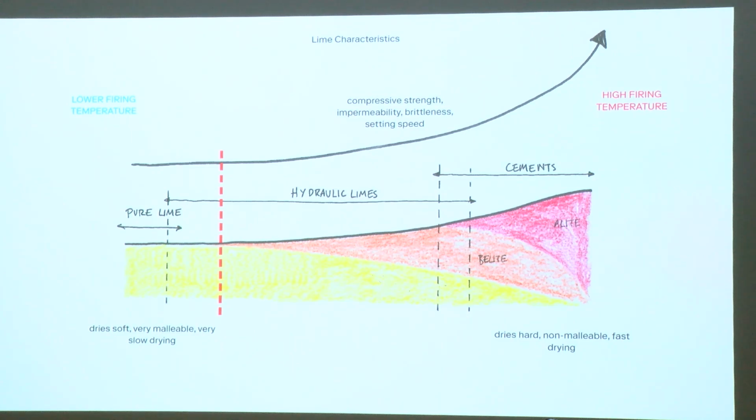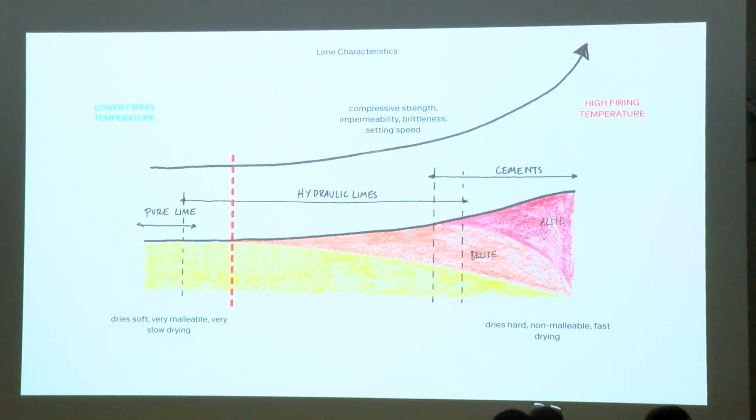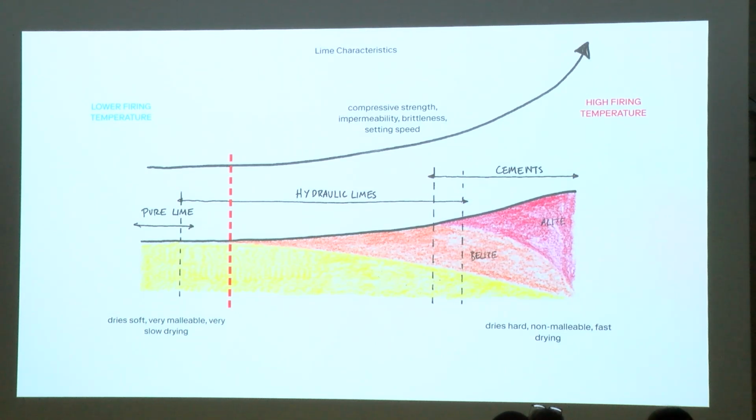So you could effectively take the brick, burn it again, and repeat that process. That's where lime becomes quite an interesting material, because you can just keep going around the cycle. And the sequestration of carbon when it carbonates is theoretically carbon negative relative to the carbon produced in the firing process. We're not using a lime at that end of the spectrum, unfortunately, but you could do the other things. You can take the bricks apart, or you can turn them into something else.